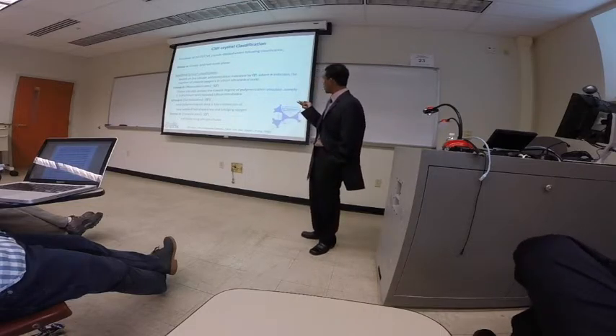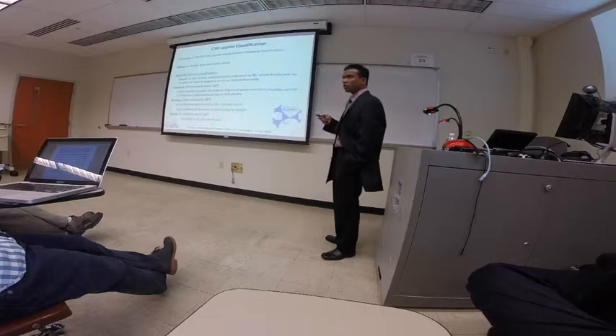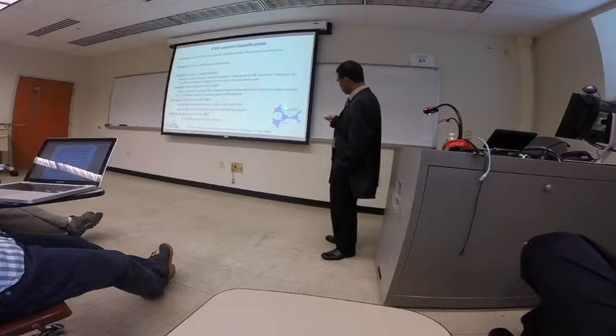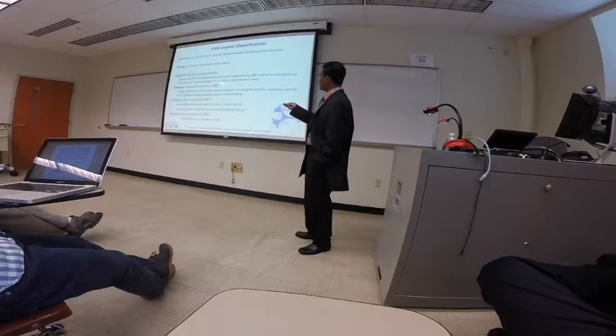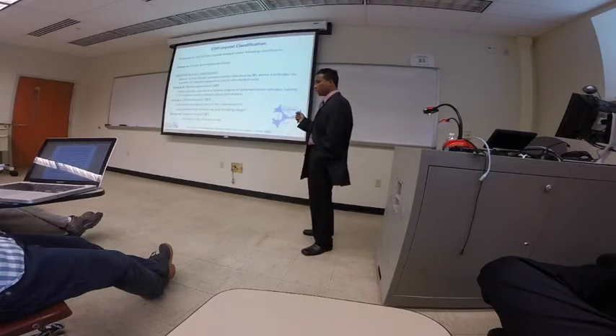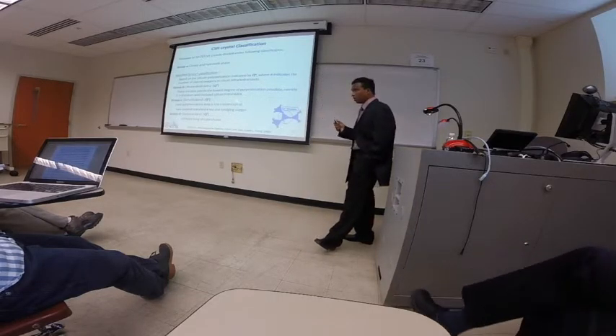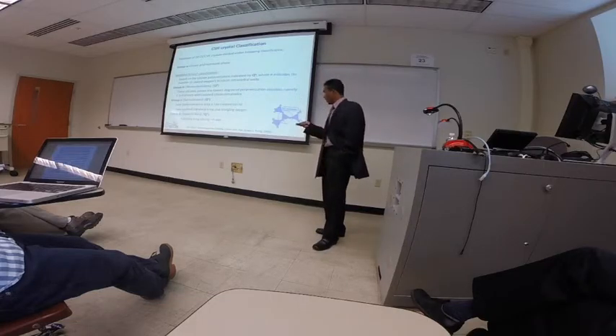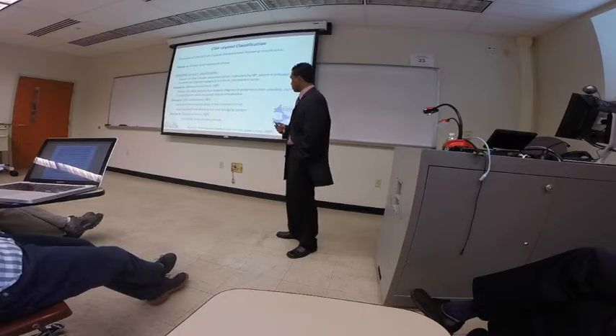The modified Strunz classification is based on the silicate polymerization indicated by Qn, where n is the number of shared oxygen atoms between silicate tetrahedra. For example, in this picture you have 3 or 4 silicate tetrahedra, and the tetrahedron in the middle shares 3 oxygen atoms, so this tetrahedron is defined as Q3. By the same logic, the group B crystals are defined as Q0, which have no shared oxygen, so they are silicate monomers. And group C, the sorosilicates, is Q1, which have one shared oxygen, which gives rise to silicate dimers. And group D, inosilicates, has 2 shared oxygens, which means the chain is infinitely extendable.